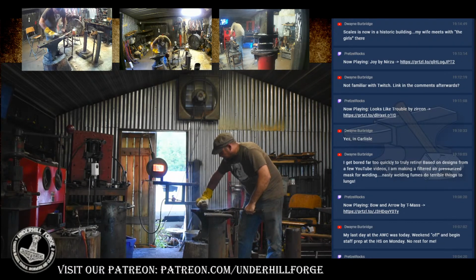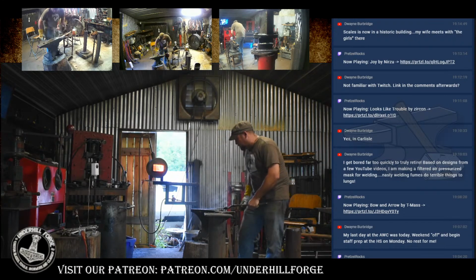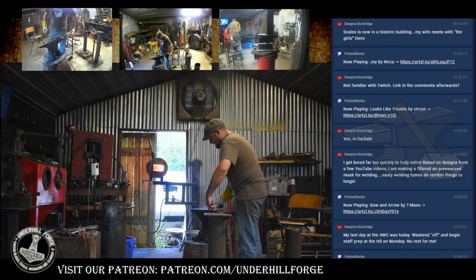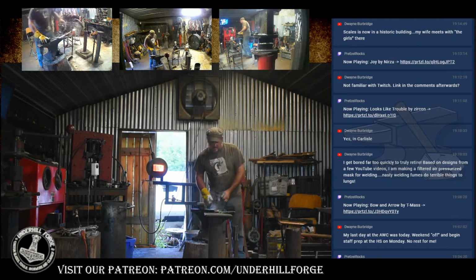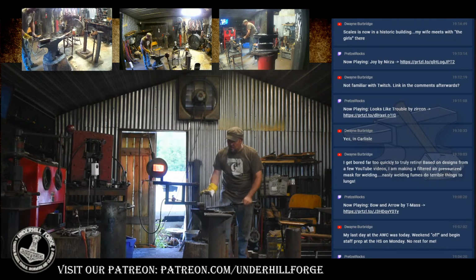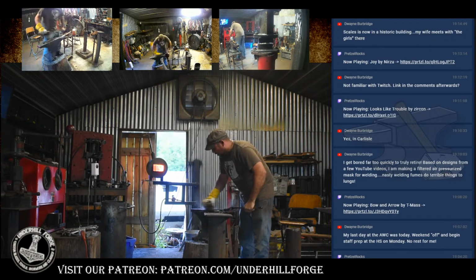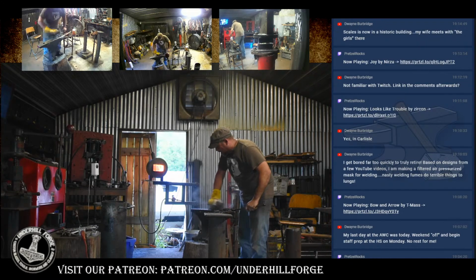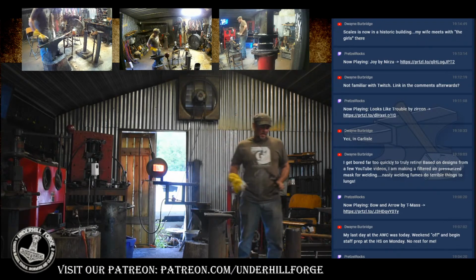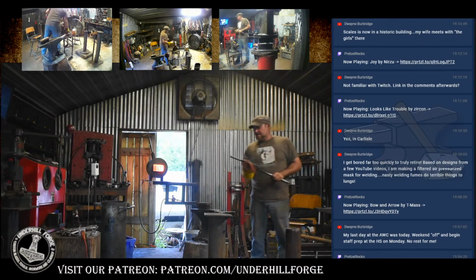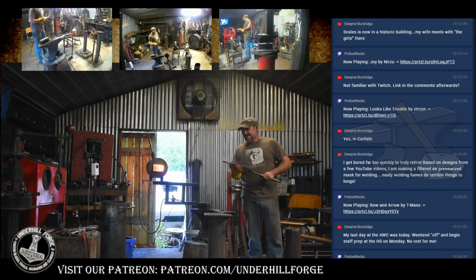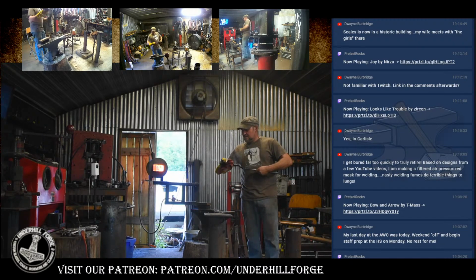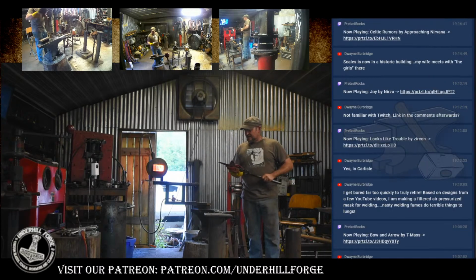The Parks 50 is not such a big problem, but when I was doing a lot of stuff in 1075, 1080, 1084, and I was using preheated canola oil, that canola oil really likes to form almost like a varnish during the heat treat process. And Parks 50 pretty much just kind of sublimates or evaporates away. But canola oil leaves a film, and it kind of thickens up and becomes sort of like shellac or varnish.